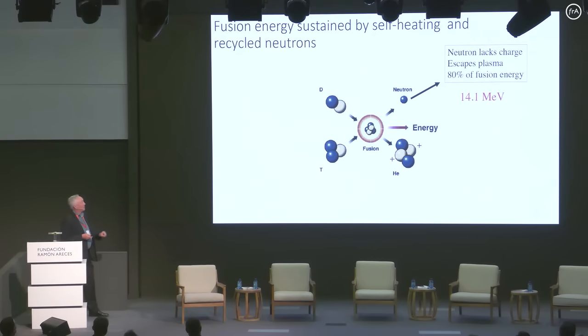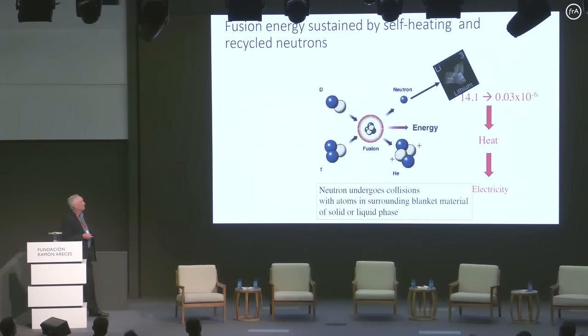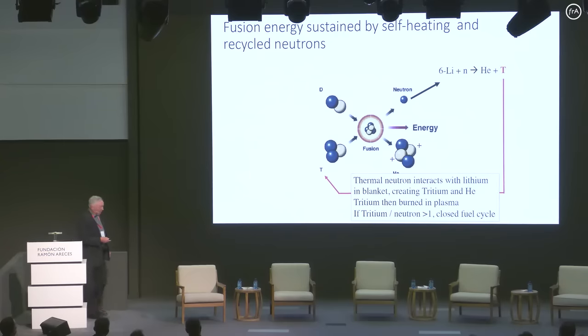What happens to the neutron? It contains 80% of the fusion energy. It lacks a charge, and so it escapes the plasma. Then you stick matter in front of that neutron, and it goes from this very energetic particle back down to room temperature. When it does this, it provides energy and therefore heat to the surrounding medium, and you use that heat, in the example I'll use, to make electricity. But in the end, fusion is a heat source. It's not really an electricity source. That has to be in the solid or liquid phase to stop the neutron. Then, when it goes back to room temperature, you actually combine this in another reaction with lithium.